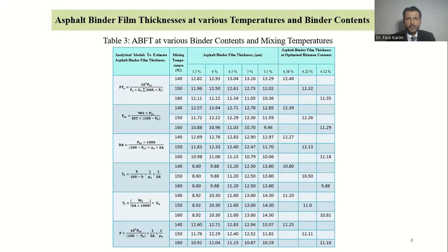So therefore, mix design was basically carried out at 3 different temperatures, 140, 150, and 160 degrees centigrade, for binder content ranging from 3.5 to 5.5%. So after calculating volumetrics, the asphalt binder film thickness was calculated using these analytical models.